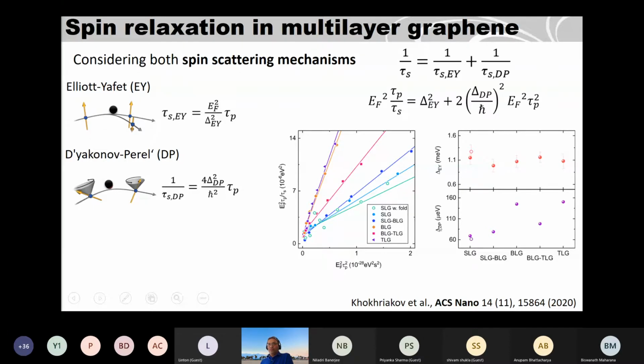But Rashba, which is actually from inversion symmetry broken systems with spin orbit coupling, for different layers, so single layer to bilayer, tri-layer, and the boundaries, it's around micro electron volt, hundreds of micro electron volt. So which is quite good for these systems. That means we need a much cleaner system to actually see clearly the spin lifetime of graphene. But these dirty systems also give a good property.